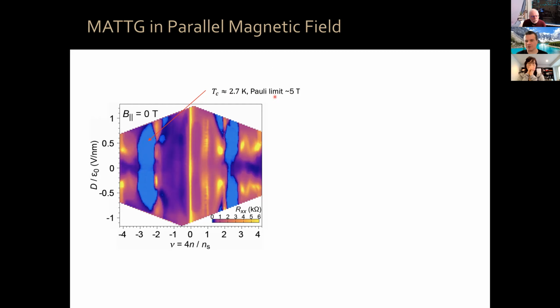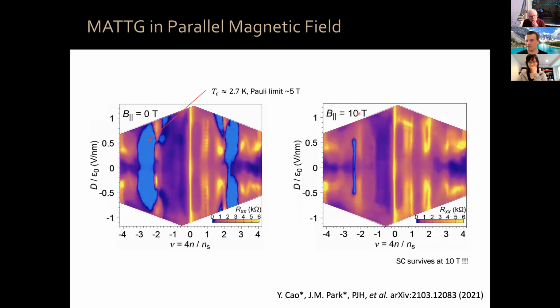That means your Pauli limit should be about 5 Tesla, okay? Superconductivity should be well gone at 5 Tesla. We measure with an in-plane field of 10 Tesla, and we see that superconductivity is very much still present at optimal doping in an extended region of displacement field, okay?